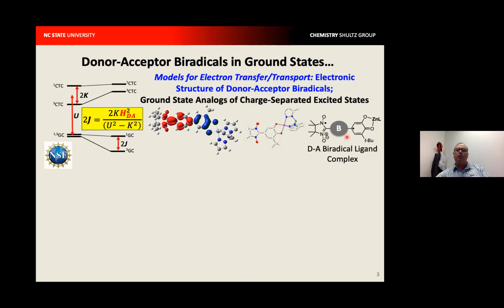By virtue of the structure of these molecules, the bridge can mediate magnetic exchange such that the singlet triplet gap that we observe is comparable to the thermal energy, and we can actually see electronic transitions out of both the triplet and singlet ground states. And so building on a known model that relates that magnetic exchange coupling to the electronic coupling, we can spectroscopically evaluate the excited state singlet triplet gap, and we can evaluate the mean charge transfer energy U, and we can numerically calculate what the electronic coupling is. It can't be determined in a straightforward fashion from other spectroscopic methods for any bridge fragment B.